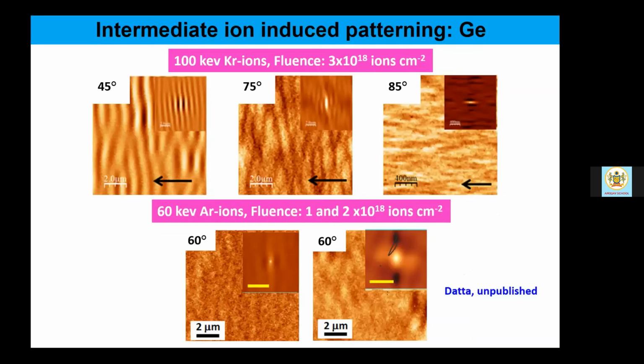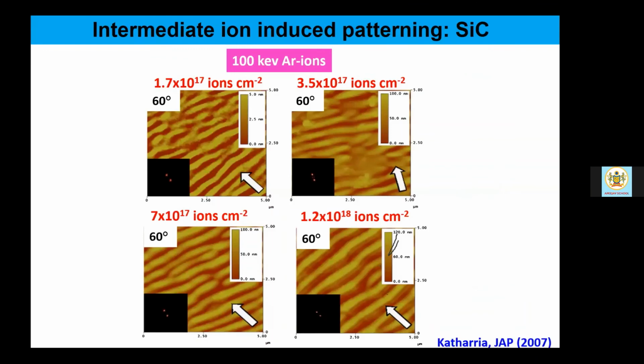Now this is the example of germanium. 60 keV argon ions lead to the formation of a very feeble kind of ripple pattern on germanium. On the other hand, the mass effect, 100 keV krypton ions are easily seen to give rise to very mature ripple formation in germanium. 100 keV argon ions can lead to very mature and nice pattern formation on silicon carbide. These are all extremely important material components for device technology. When you talk about high-speed electronic devices, these are extremely important materials.